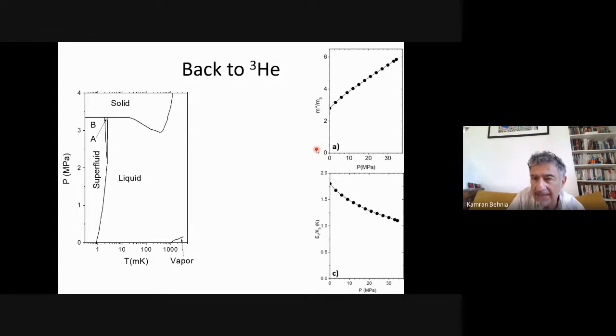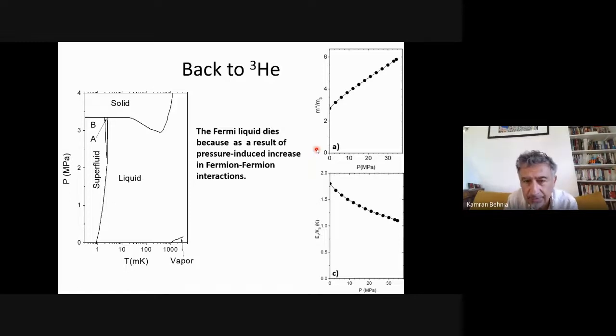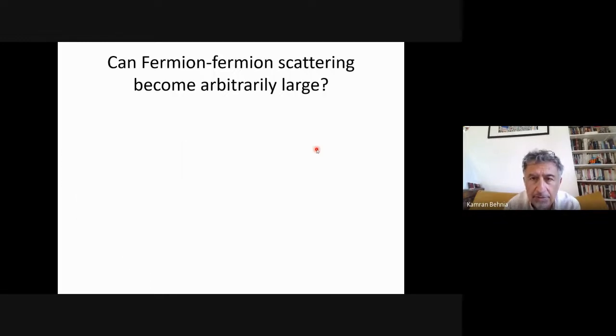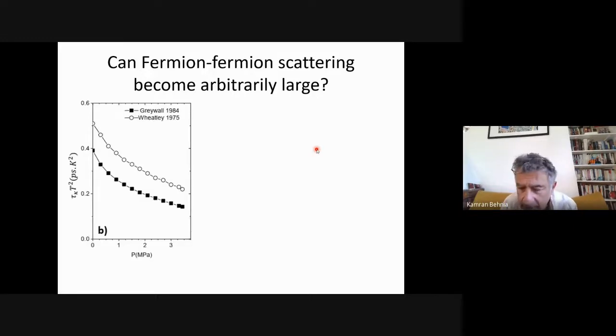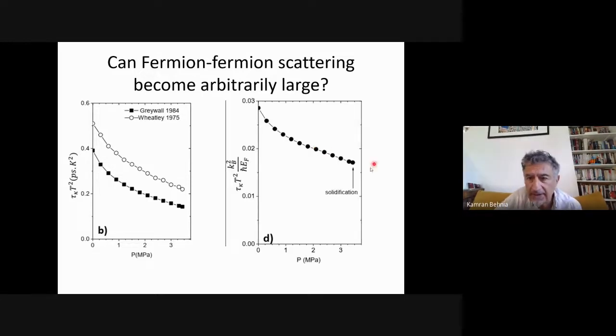So let me come back to helium-3 and mention one thing. We know that mass increases when you put pressure, and the Fermi liquid eventually dies because the more pressure you have, the larger is the amplitude of fermion-fermion interactions. Now, here is the question. Why does the Fermi liquid disappear in helium-3? One thing that we can say is that you can define there a kind of dimensionless amplitude of T-square resistivity, in the sense that if you take the scattering time, times T-square, multiply it by the Boltzmann constant squared and divide it by the Fermi energy, you find a number which is extremely small. Then here you have a sudden solidification. The system suddenly becomes a solid.